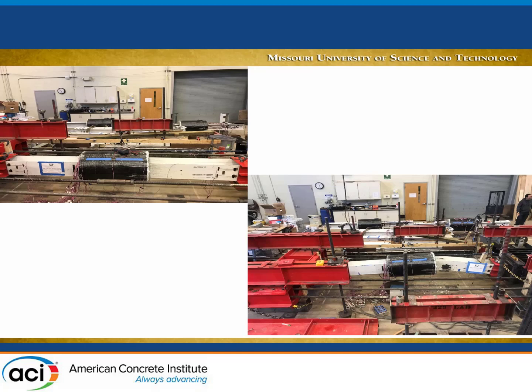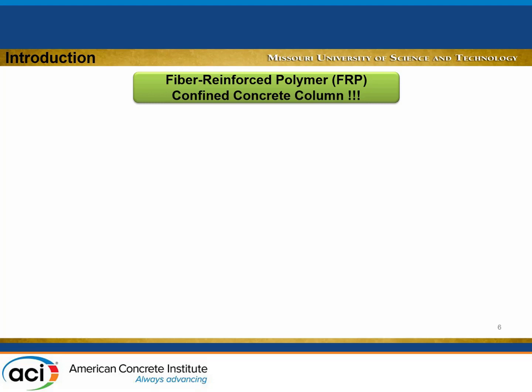So over here we just use carbon fiber. Here is the pile after the repair. Actually, we're able to restore very close to 90% of the capacity. We tested these piles until fully yielding, buckling and so on, and then straightened them, repaired and retested. We were able to restore about 90%, not of the capacity of the corroded piles, but of the squash load, the yielding load of the pile. So this was one option, to repair whatever you have.